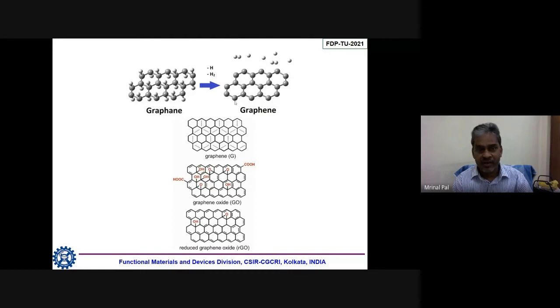Then if we talk about graphene oxide, particularly if we use the chemical exfoliation process, as I mentioned earlier, it is first oxidizing, then reducing. While oxidizing using potassium permanganate, it becomes a single layer, that is fine, but a lot of oxygen and OH groups will be linked with it, and COOH groups will be there. So that is called graphene oxide.